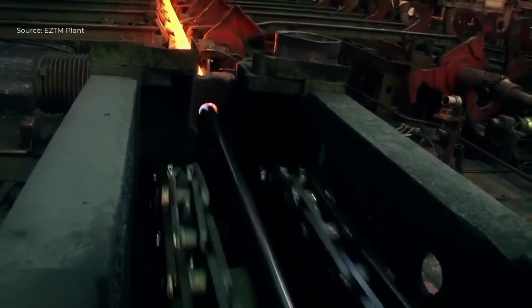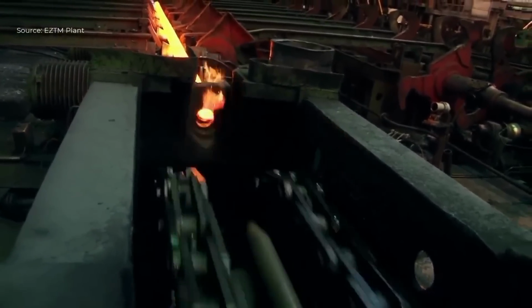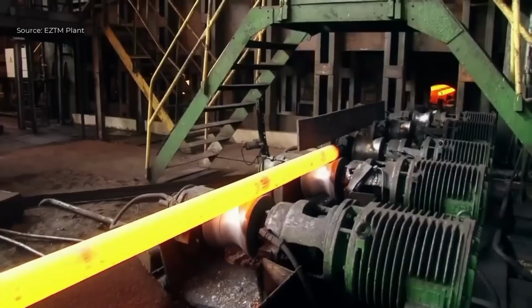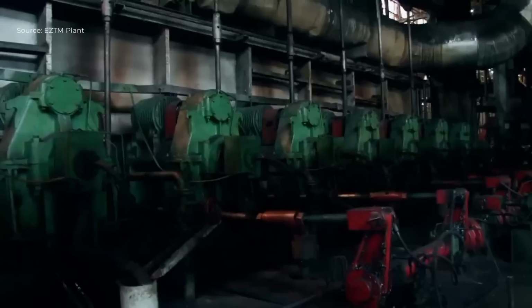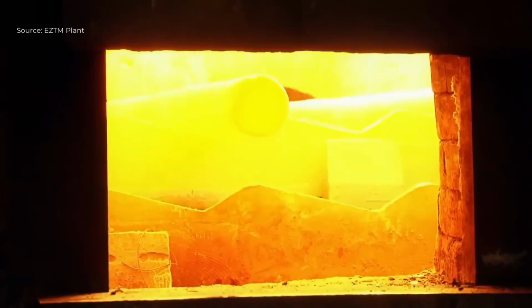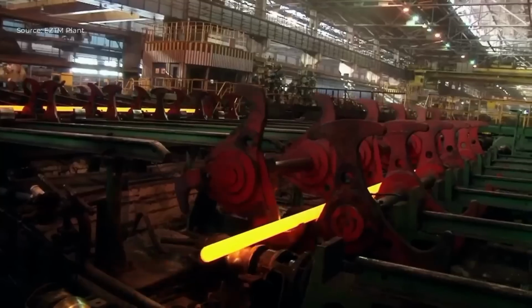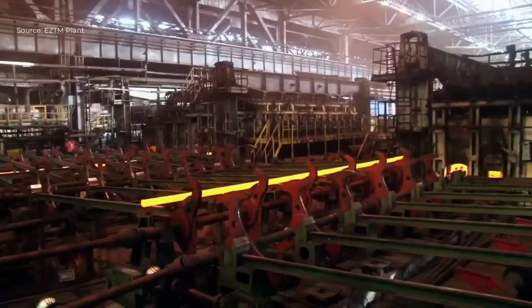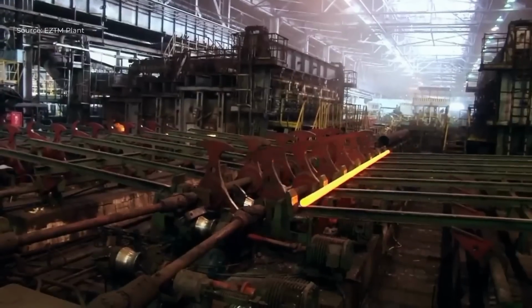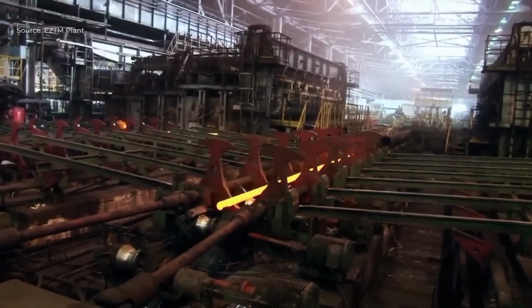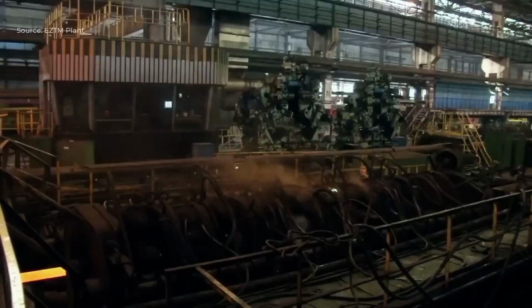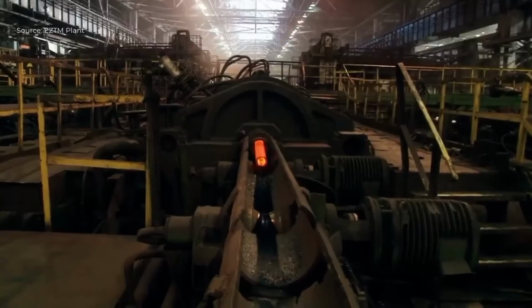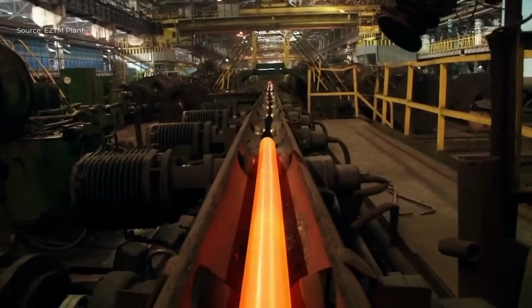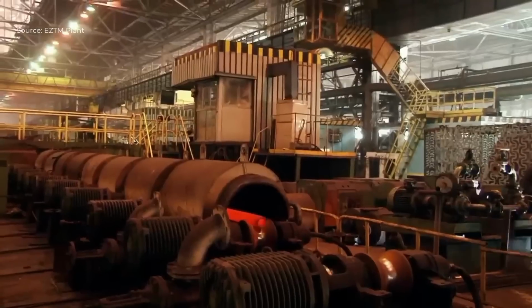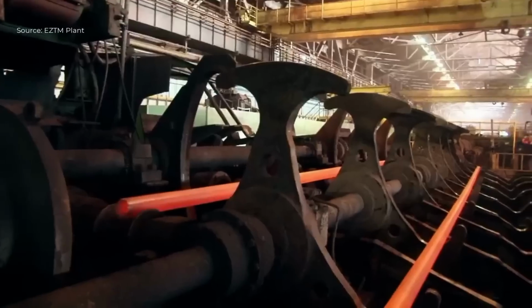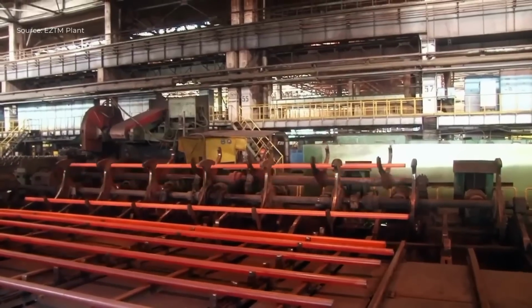For producing pipes, a fixed mandrel is inserted along the axis to form the inner cavity of the pipe as the metal flows around it. This results in the formation of a seamless tube with a circular cross-section. The extruded pipe exits the die at high temperature and is guided along a run-out table, where it is cooled with water.